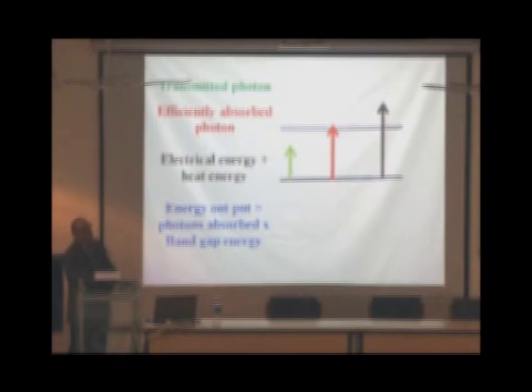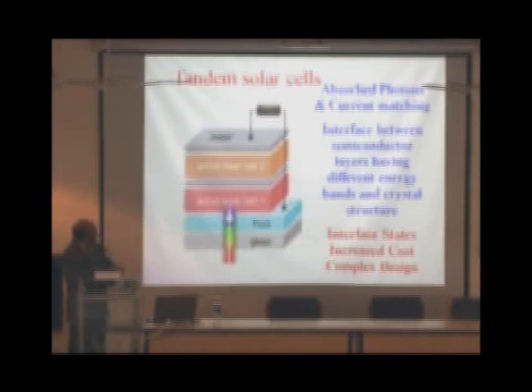What is required in a solar cell is that you cannot work efficiently with a one band gap or one junction solar cell. And normally in thin film technology, people don't use just one, so you have to use a large number of solar cell materials, each consisting of a different semiconductor and hence a different band gap. So if you have the active layer cell 1, which will absorb one particular type of photons, the other photons will be transmitted through it to cell 2 and cell 3 and so on. But it becomes a very complicated design because the number of photons has to be counted, that is, each layer should absorb the same number of photons because the current has to match. The current which is produced in cell 1 and cell 2 should be the same.